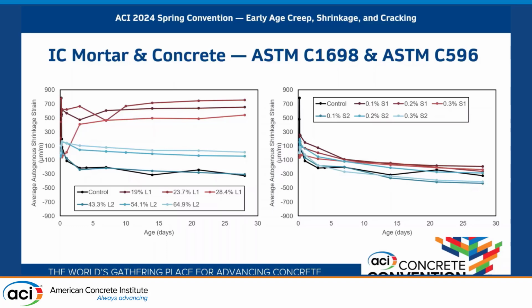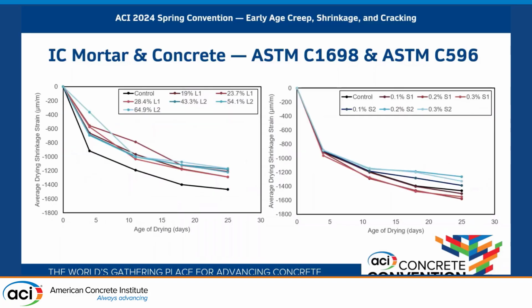This is a closed system test, so there's no moisture loss due to drying. It's only the autogenous change from these material hydration processes. In this case, this is, I believe, the 1698 results for lightweight aggregate and SAP.